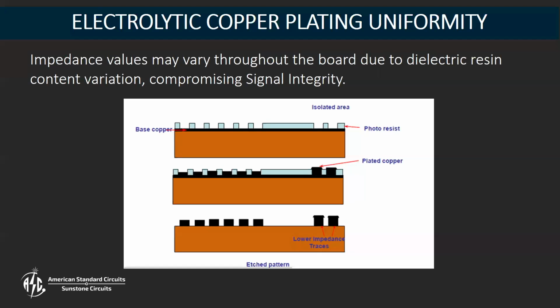If you're thinking of it from an impedance standpoint, where the cross-sectional area of that trace is important for overall electrical impedance factors, you can see the traces on the right have significantly more cross-sectional area because of the mushroom on the top, as well as the overall height of those traces compared to those on the left. So especially when you have impedance requirements, try to keep the copper area nominal around them. Adding thieving or planes around them tends to help make those traces a little more even and better performing in your impedance designs.